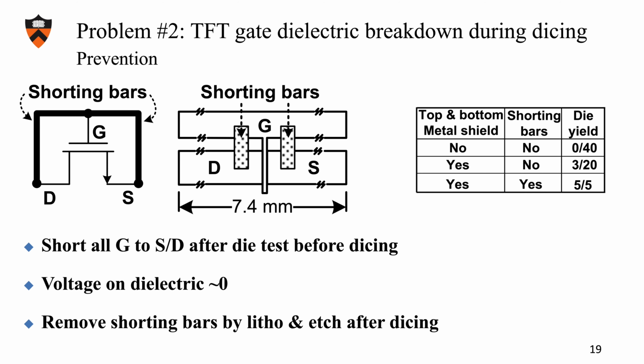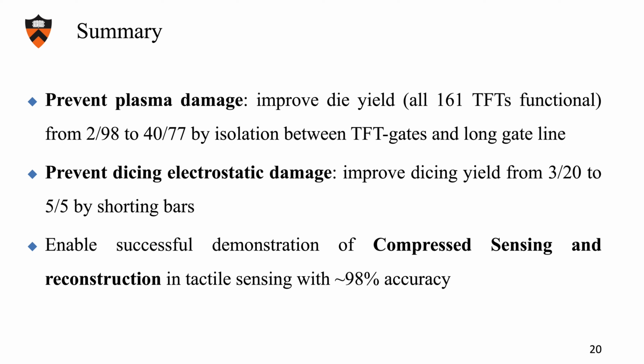To summarize, in this work, we prevented plasma damage and improved the die yield from 2 out of 98 to 40 out of 77 by isolation between TFT gates and long gate lines. We also prevented dicing electrostatic damage, improving the dicing yield from 3 out of 20 to 5 out of 5 by shorting bars. This enables successful demonstration of compressed sensing and reconstruction in tactile sensing with 98% accuracy.